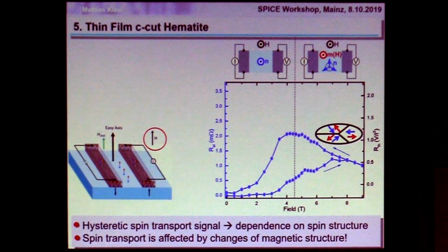So you'd love to do this experiment in some imaging facility where you can see how many of the domain walls you have removed. I can tell you that in bulk crystals of hematite, it goes to 10 microns. So fundamentally, in the material, 10 microns is possible. But of course, you might have higher damping in the thin film. So the intrinsic length scale limited by the damping in thin films might still be lower than in the bulk. But fundamentally, in Fe2O3, you can transport spin over a length scale of 100 microns.